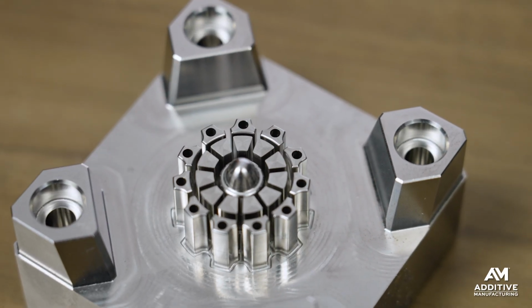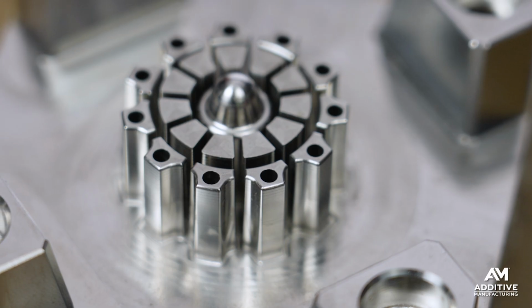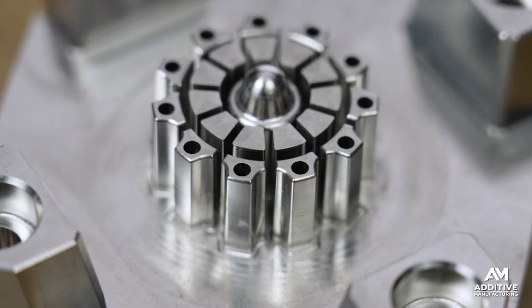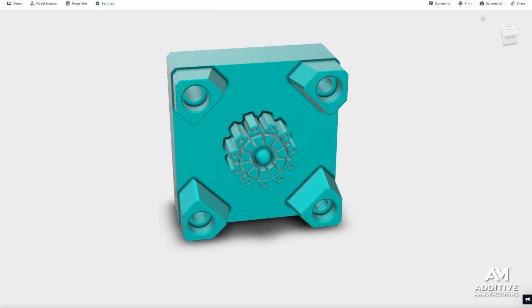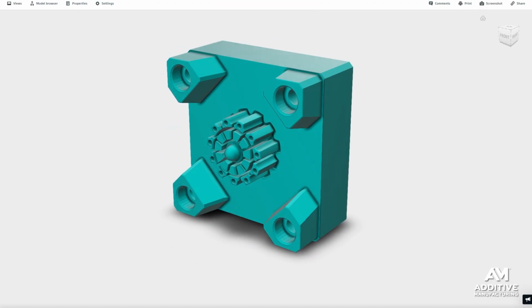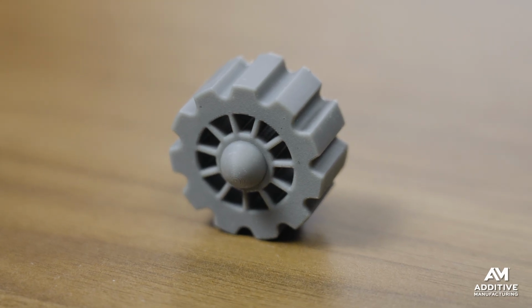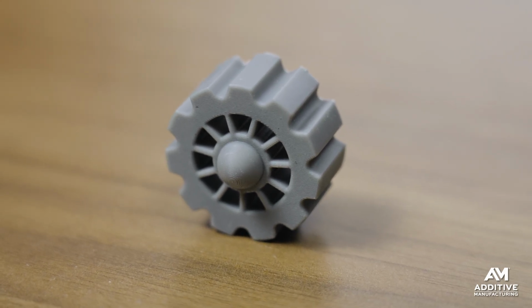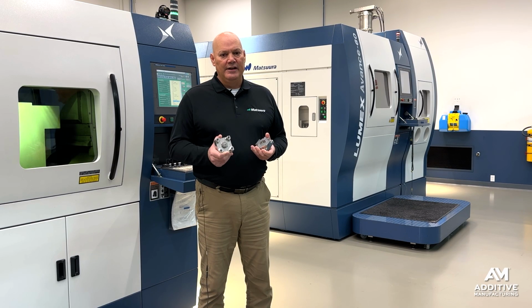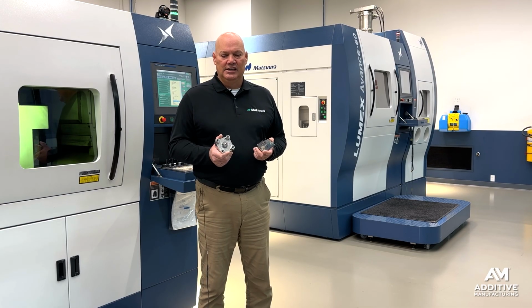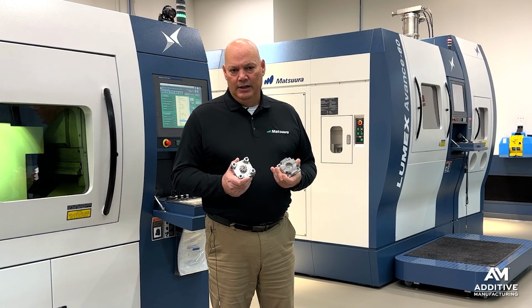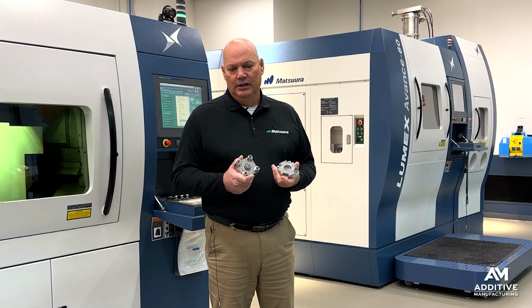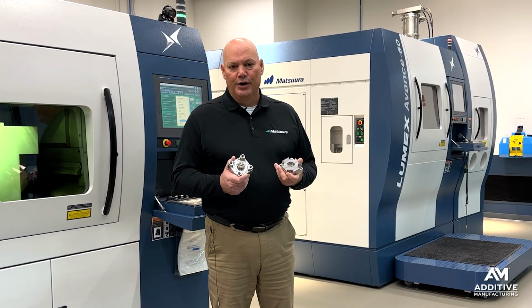The first test out of the gate, we eliminated all of the burning of the deep ribs through that porous process. By optimizing a little cycle time, we took that 10 seconds out of the cycle, still 5 seconds longer than they wanted, but certainly a significant improvement from where they were at. And the beauty of it is instead of 4 weeks for this cavity, we built the cavity and core set in 4 days.